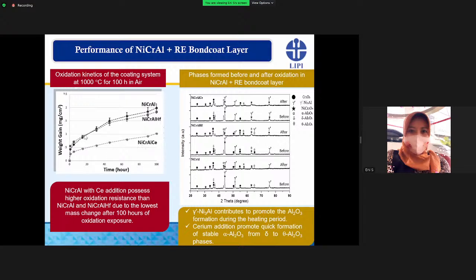This shows the oxidation kinetics. The mass gain increases gradually with time, and all 3 samples follow the parabolic rate law. The result shows that the nickel, chromium, aluminum with hafnium addition show a similar mass gain of around 1.8 to 2 milligrams per centimeter square, while the sample with the cerium addition has a higher oxidation resistance, with a mass change of only 1 milligram per centimeter square. And this figure shows the XRD pattern of those 3 coating samples.